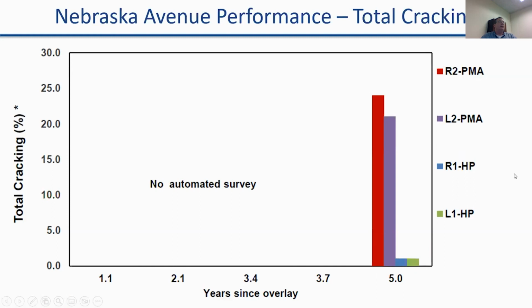You're around 20 to 25% total cracking in the 2 outside travel lanes with conventional mix, and then you're somewhere around 1 to 2% in the 2 high polymer lanes. So, big difference. You're getting your value there easily.